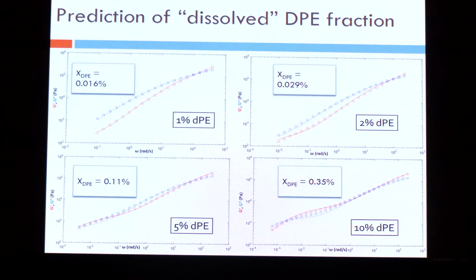So if I take 1% disentangled polyethylene, I put it in, mix it with 99% high density polyethylene, I mix them and hope that some of it dissolves. How much dissolves, the theory predicts, is hardly 0.016%. Out of that 1%, a very small fraction actually ends up really molecularly dissolving. And you will see the same thing for almost all others. So for example, the bottom right, I'm putting in as much as 10% disentangled polymer and only 0.35% really dissolves in the matrix phase. But look at the rheological changes.